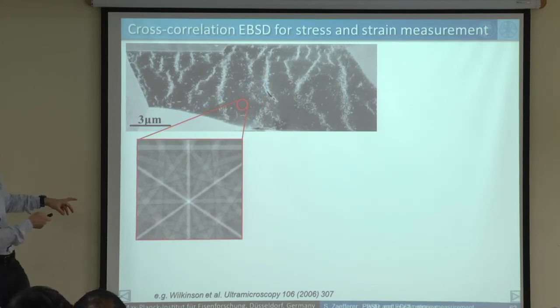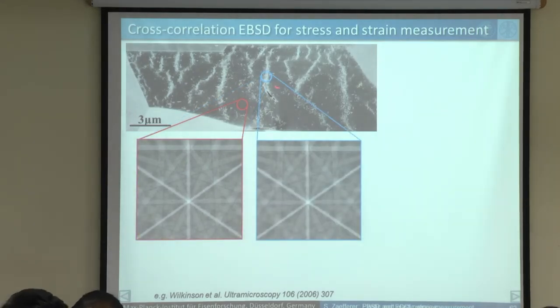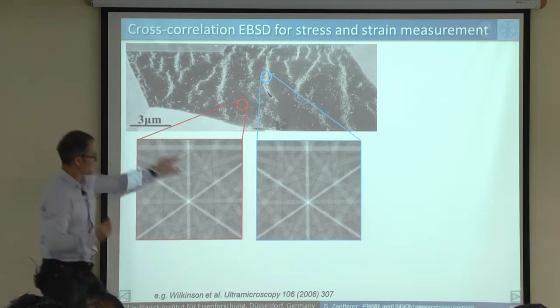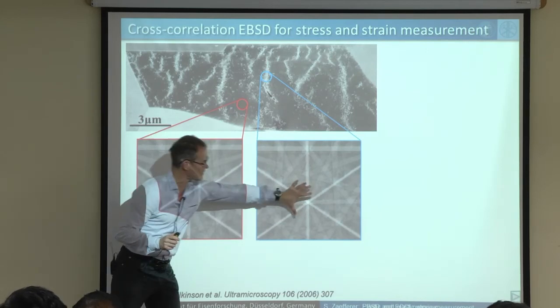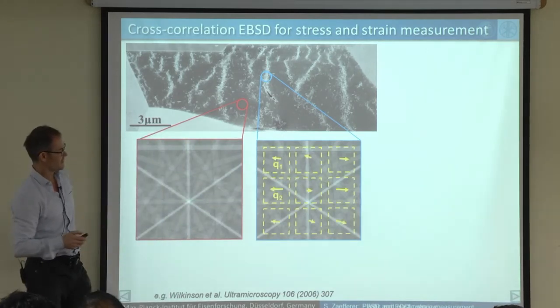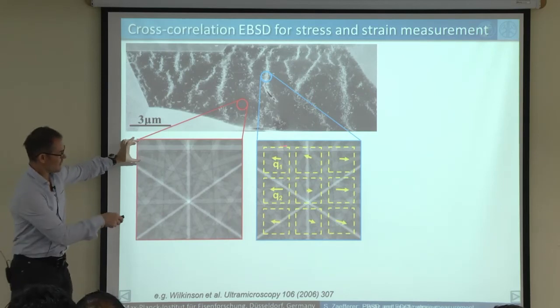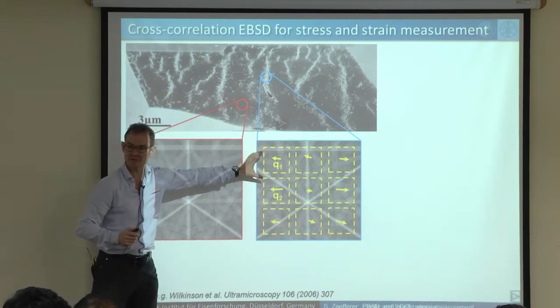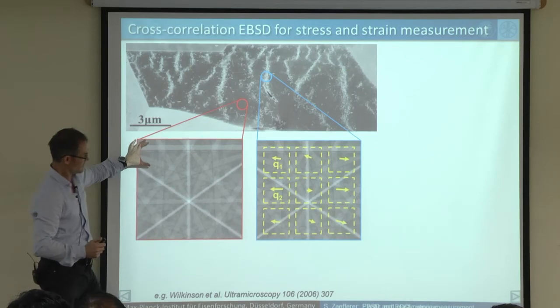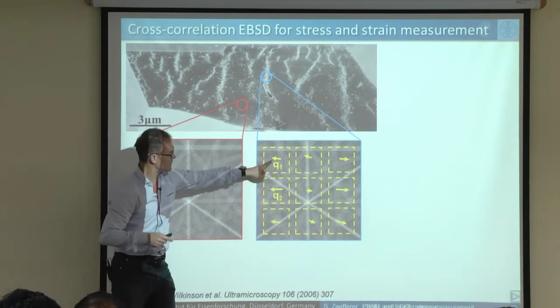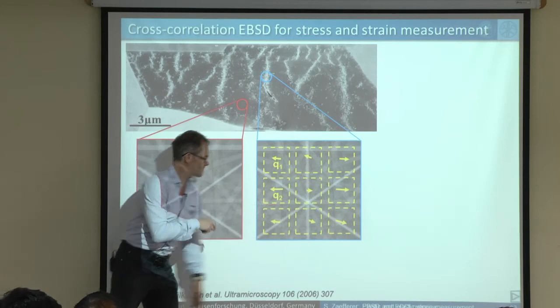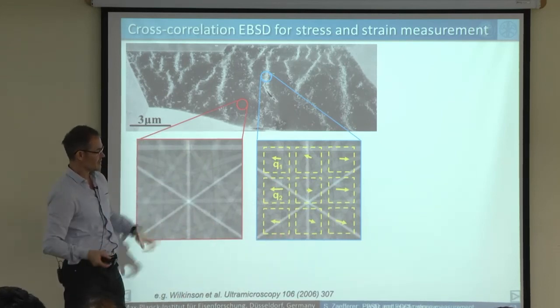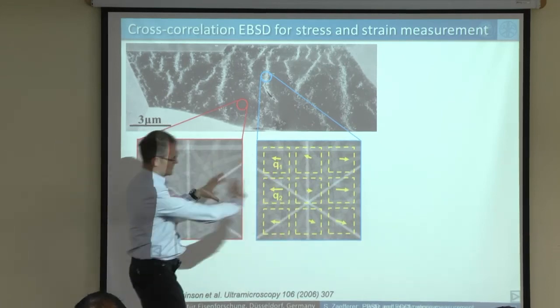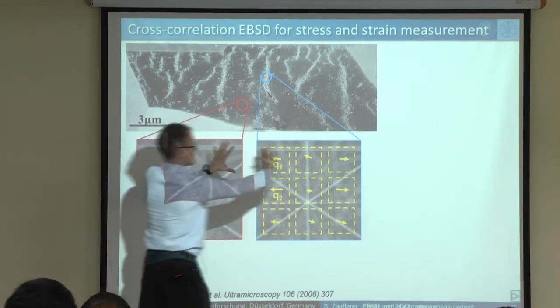Yeah. So now we put these two patterns next to each other, one from that side and one from that side, and we compare pixel by pixel how this pattern is changed with respect to this one here. So we actually make little areas, and for every area we calculate how this area has been shifted relative to this reference area. And we draw this shift in form of a little vector into each of these regions of interest. And you find in this case maybe it has been just strained in both directions here. So there's probably a linear expansion here.